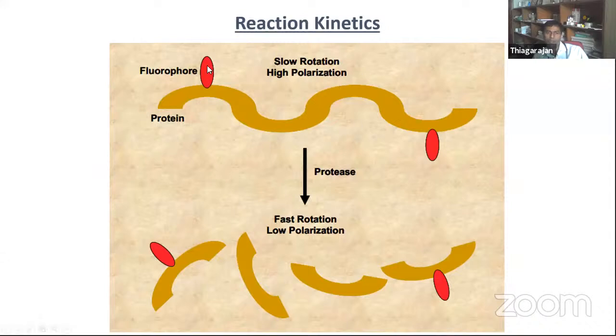So we can attach the fluorophore to the biomolecule and record the polarization. If this is a large DNA, for example, and any enzyme cleaves the DNA, then it becomes a small molecule. Before cleavage, these molecules have higher anisotropy. After cleavage, the molecule rotates very fast because it's small, so we cannot get any anisotropy. From this, we can find out whether the cleavage occurs or not, whether the enzyme works or not. Those kinds of information we can get from it.